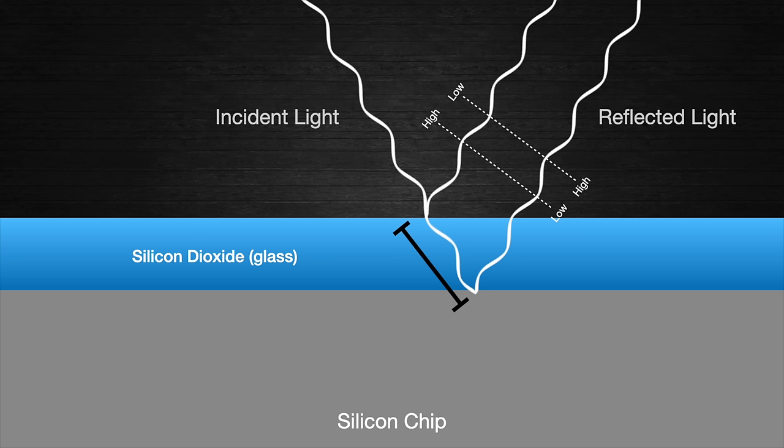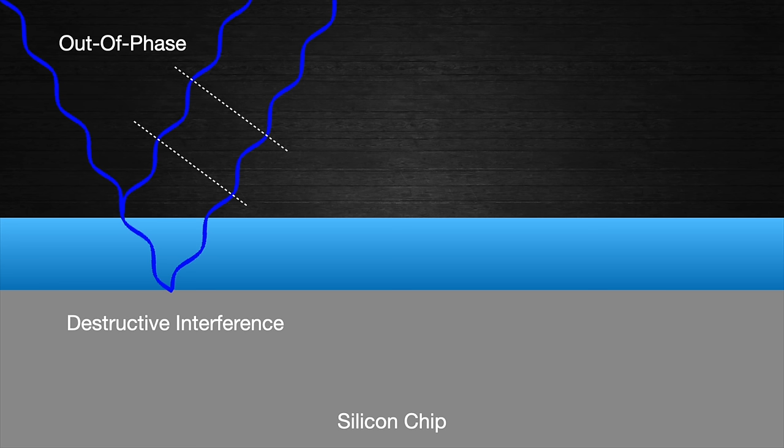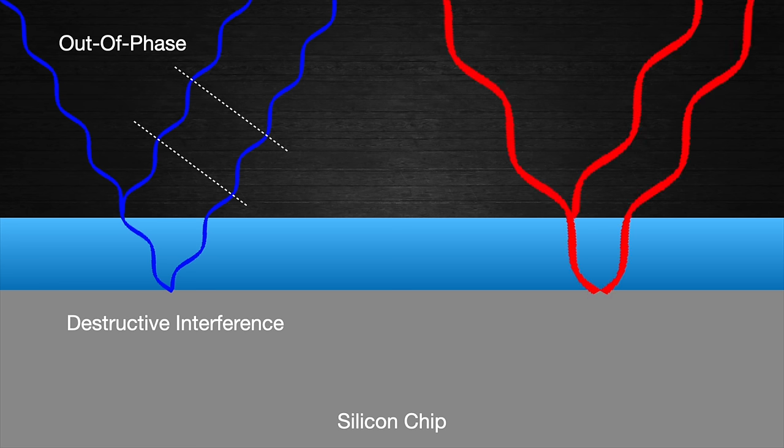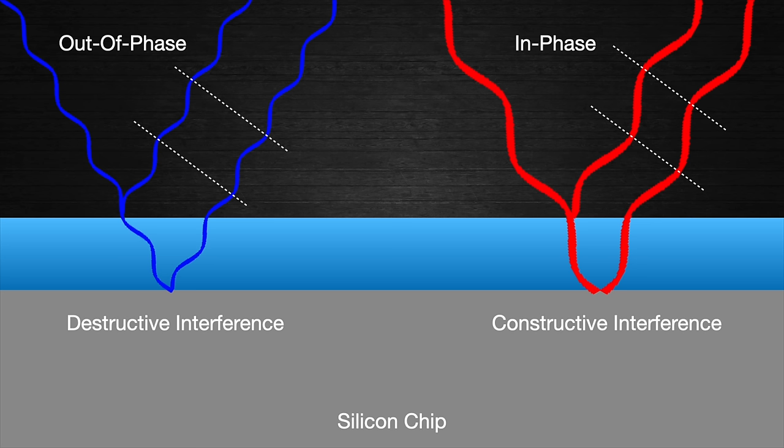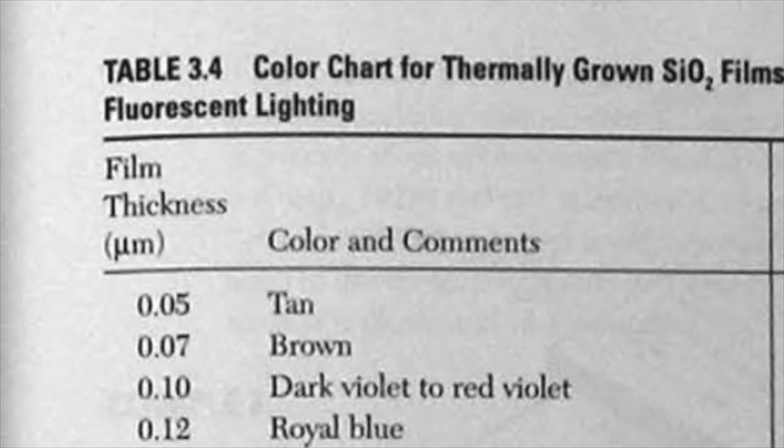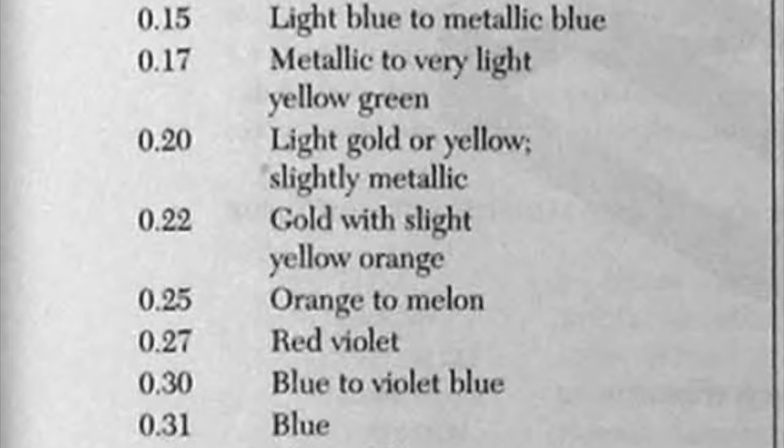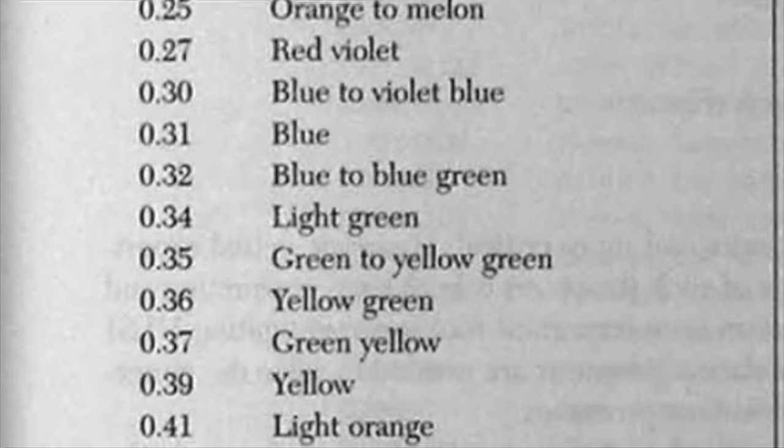The light that is reflected off the silicon surface took a longer path than the light that was reflected off the oxide surface, which means that the two light sources are no longer in phase. This causes the two reflected light sources to interfere. Since white light contains multiple wavelengths, some of the reflected light, blue in this case, will interfere destructively and become more dim. At the same time, other colors will have their light reflect back in phase and interfere constructively, which makes them brighter. Because white light contains all wavelengths, these effects combine, and the white light reflects back as a different color entirely. The exact color you see will depend on the thickness of the oxide layer.